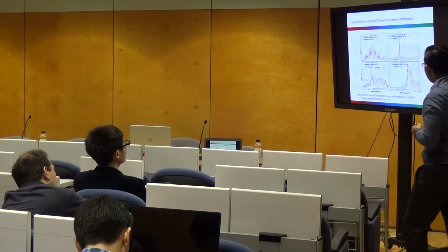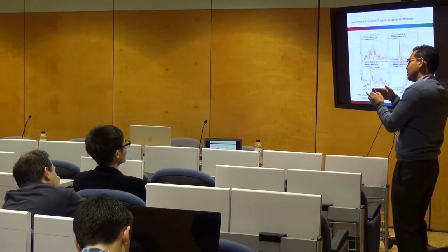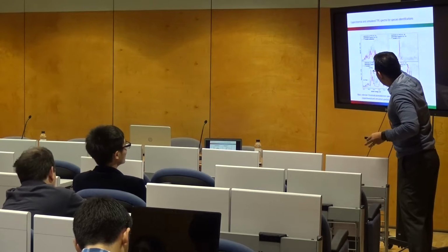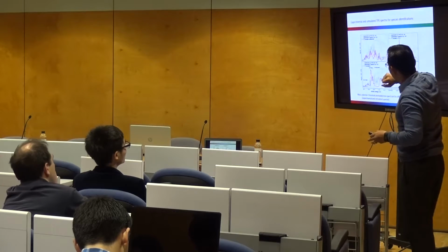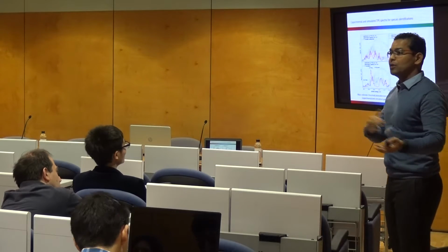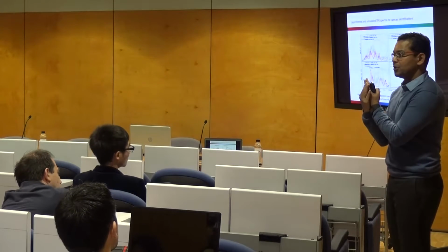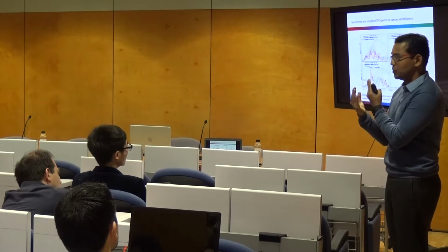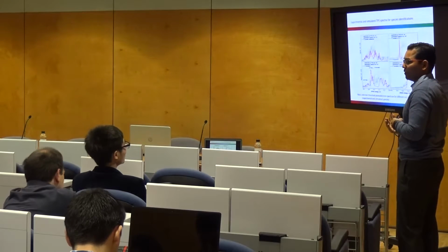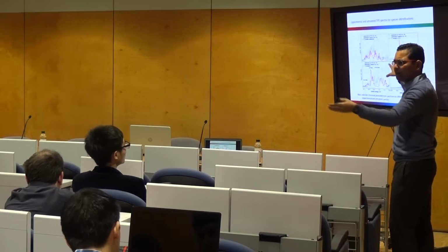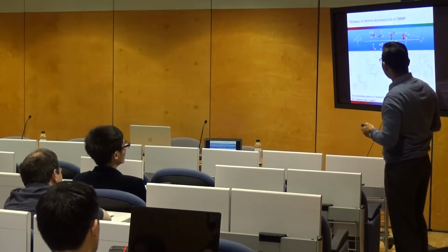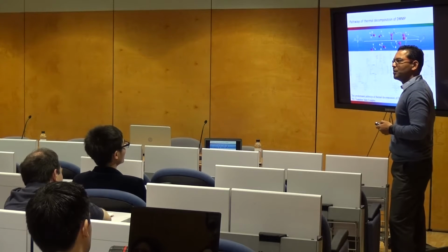What is quite interesting is we also collect the energy diagram of the electrons which are being ejected. Now these are the plot, I would say. So what we try to do is we compare the experimental value to the simulated value. If there is a match, well, we have to do a lot of calculation. If there's a match, then we can clearly say this is the species which are formed. Okay? And it takes a lot of work. I would say I think a few months just to analyze the data to be able to come up with this kind of pattern or this kind of fragmentation, I would say.